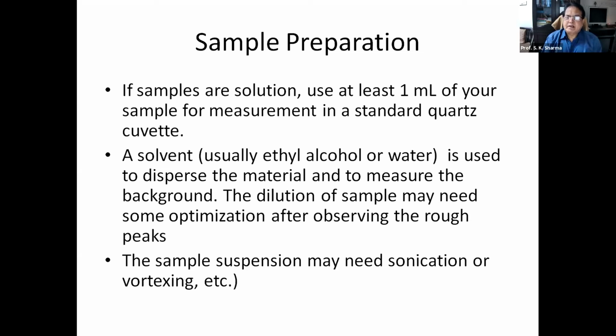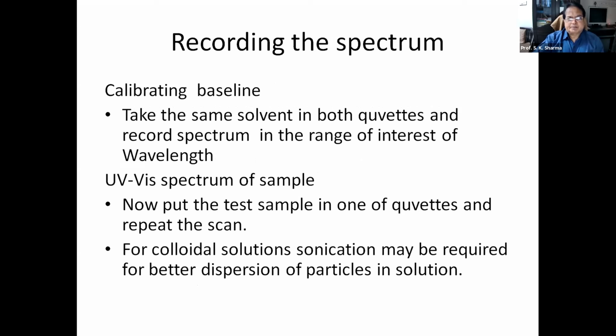And the sample suspension may need some sonication or vortexing. Why? Because sometimes your particles are so heavy that they settle down immediately inside the cuvette. So for a better recording of the spectrum, they must be floating in the solution like a colloidal solution. Unless there are particles in the path of the beam, nothing will be observed. So it will be a spectrum corresponding to the solvent only. So we need to sonicate it so that all the particles are uniformly dispersed in the solution.